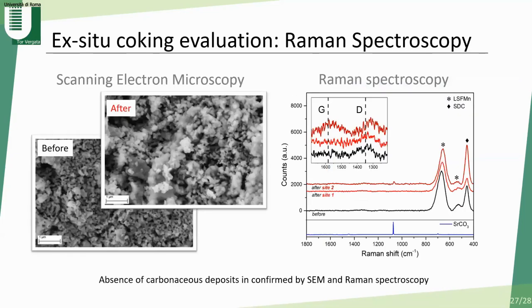We checked the coking, removing the cells and checking by SEM and Raman spectroscopy. From SEM, we could not detect anywhere on the surface carbon filaments due to the carbon deposition or carbon coking. We can just observe a slight increase of the grain size after prolonged exposure at high temperature. And from Raman spectroscopy, here we have the G and D bands, which are typical of deposited carbon. We couldn't say clearly that there is any carbon deposition. Those peaks are related to the iron, they're related to the samples, not to the carbon. So here there is the window for the carbon peak.